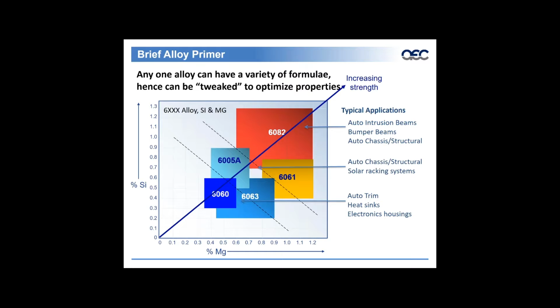Here's just a brief primer in regards to alloy. Any one alloy can have a variety of formulas and hence can be tweaked to optimize properties. What we're looking at here is a graph that shows the silicon content on the vertical axis and the magnesium content on the horizontal axis. The lower silicon and magnesium content, represented by a 6060, is typically used in auto trim, heat sinks, and electronic housings. However, we saw in the example of Lotus that it was utilized in a more structural application as a result of the geometry that was applied to that alloy.